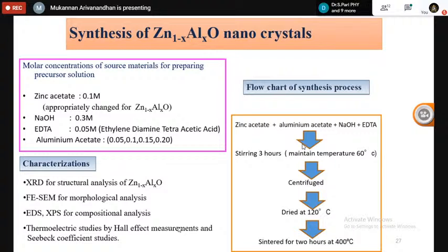Okay, so this is another system, aluminum substituted zinc oxide. In that, a similar procedure has been followed and synthesized by the solution process, and the protocol is almost the same. The aluminum content has been systematically varied, and we have made the sample as a powder and as a pellet and subjected it to the basic characterization as well as the thermoelectric analysis.